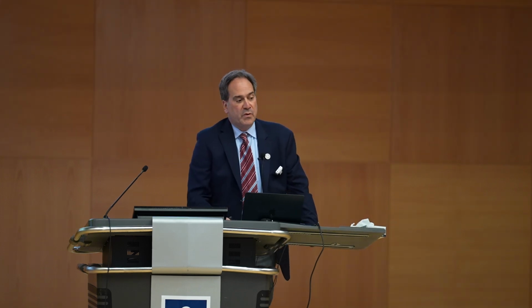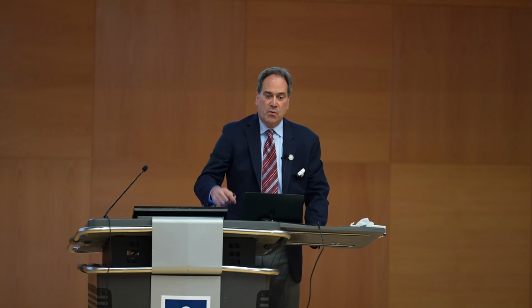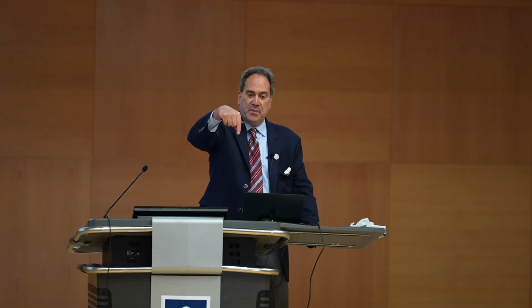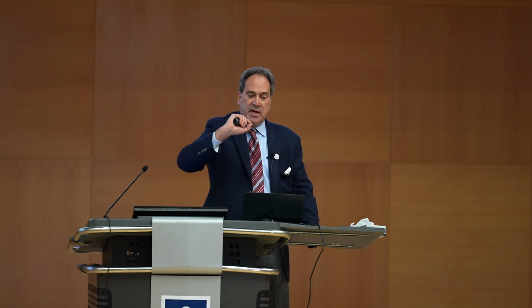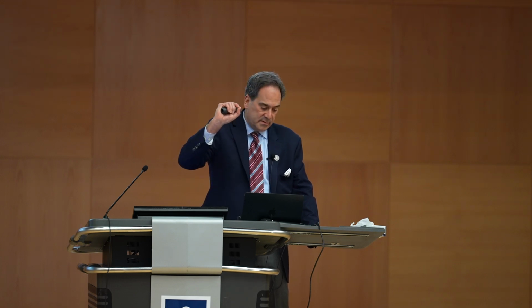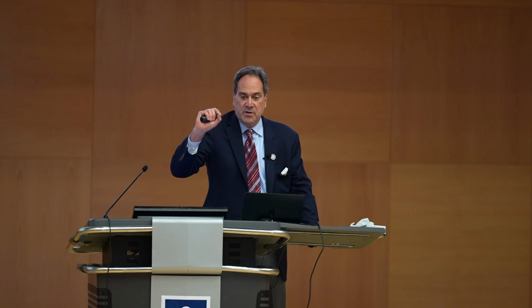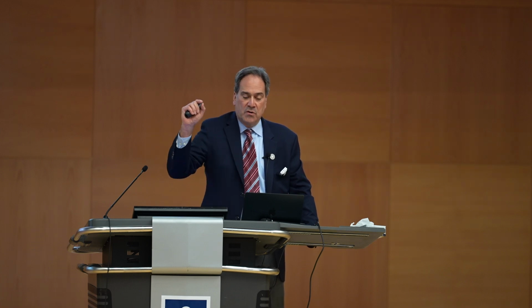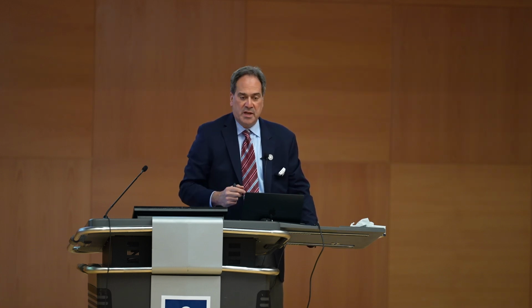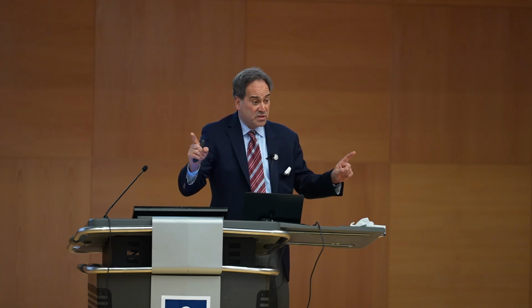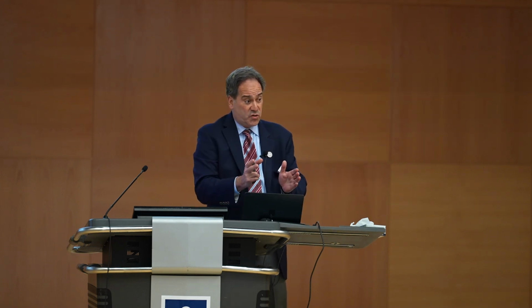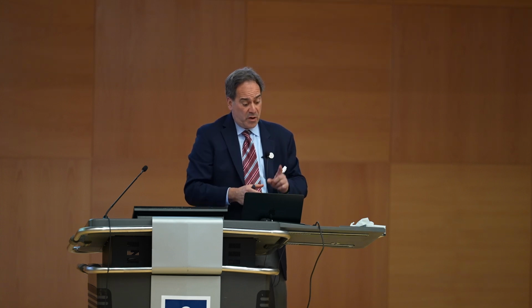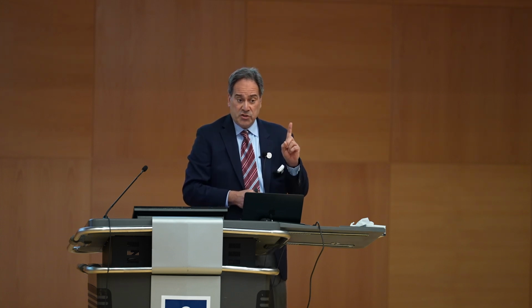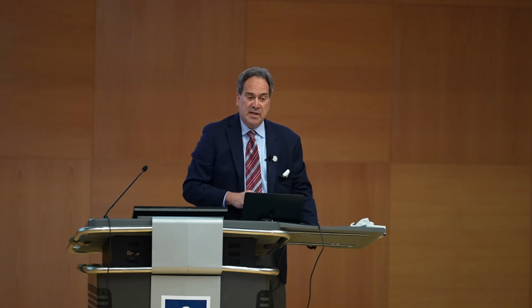Does it work? Well, we start with tetrachloroauric acid, a gold salt, and you can see in the lower left here, it works remarkably well. If I put down a tip and touch it lightly, I can make a tiny reactor, maybe call it 170 nanometers in diameter. If I hold it for a longer period of time, it grows in size up to about 220 nanometers in diameter. That's the reactor size. When I post-thermally treat, I end up getting gold particles, a single particle in every feature, and it correlates with the size of the reactor.